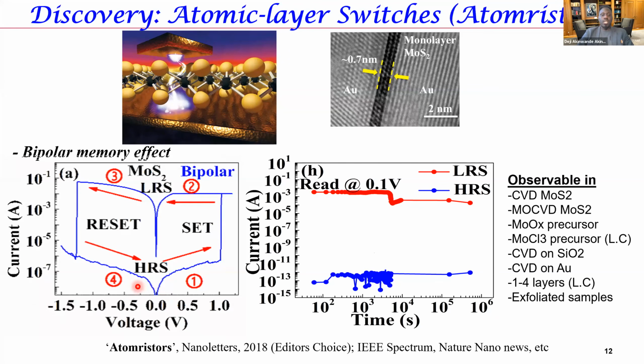At very low voltage, initially it's very low current - that's the high resistance state, let's say binary 0. Then around 1 volt, corresponding roughly to electrical fields of 1 volt per nanometer, you suddenly have the switching effect where the current jumps. So then you get a high current regime, or low resistance regime, which we call the low resistance state.